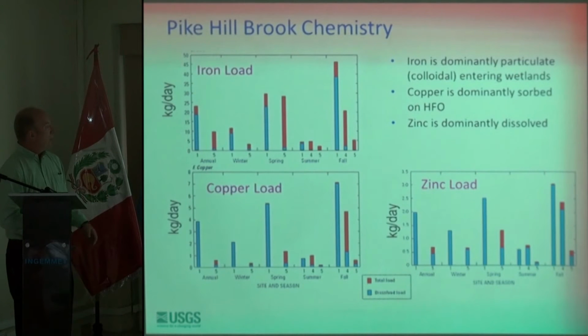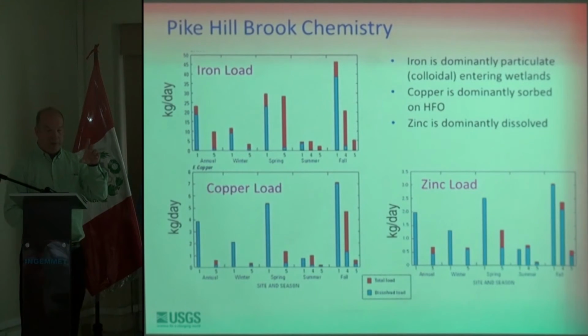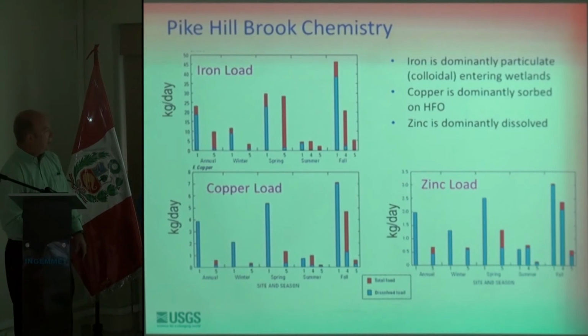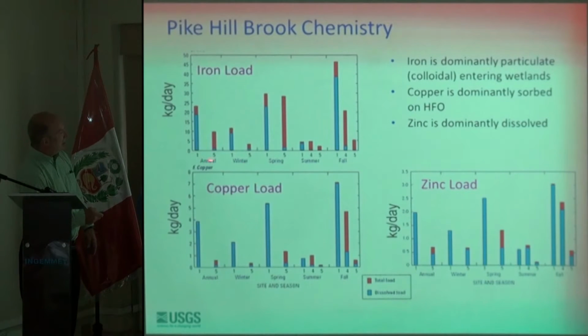When you look at the loads that are coming downstream, you can look at both the dissolved loads, but also the fine particulate loads, which is what we're doing here. So here I've got loads of iron, copper, and zinc shown for different seasons at the three different sites. When we initially started the site, we only had two sites and decided that we needed to add that middle one.